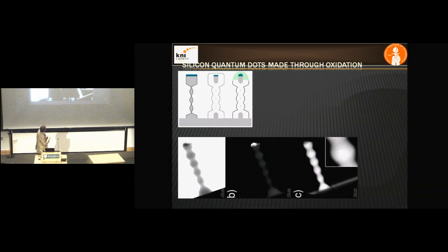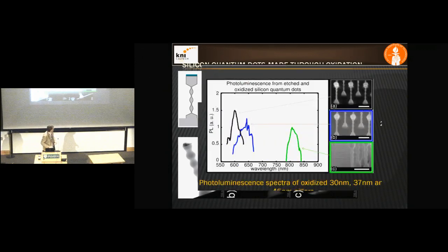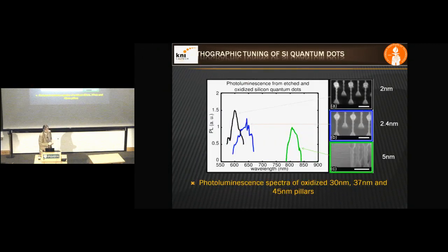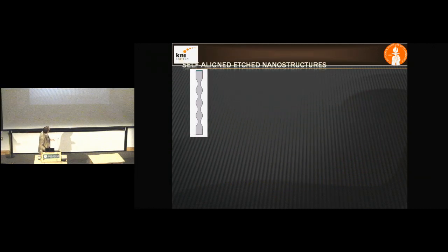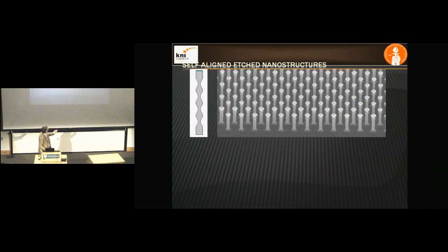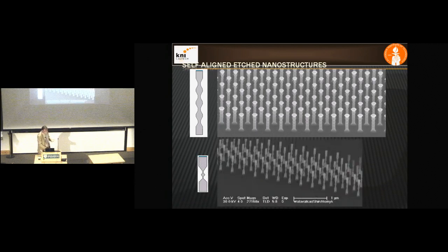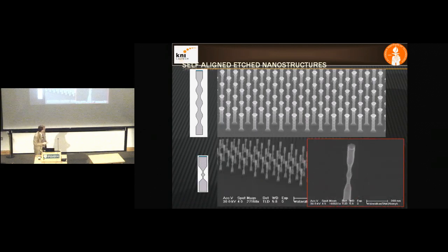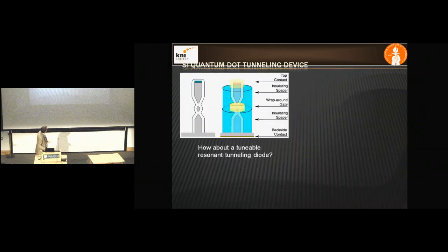And then if you oxidize that, you end up having little dots, little quantum dots. And these quantum dots, again, show you the blue shift. What I like about this figure is you see the difference between a 2 nanometer and a 2.4 nanometer silicon quantum dot that you've made. You've added 1 atom, okay? And you can see it. It's really cool. So basically, the whole idea is you can now make these kinds of nanostructures, essentially 3-dimensional nanostructures, by doing a combination of lithography and careful etching. Okay? This is a really neat direction, I think.